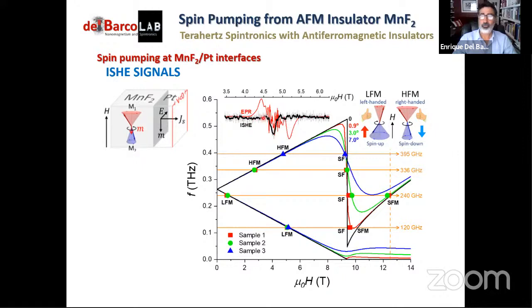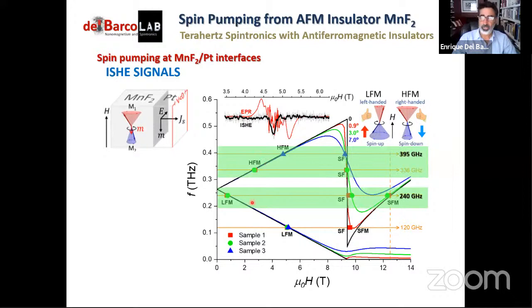But the same doesn't apply to the electric signal. In all cases, all these dots, we have the electric signal exactly where we have the center of the spectroscopy signal. And from now on, I'm going to show you results at two different frequencies. One low frequency, where we can explore the low frequency mode, the spin flop transition, and the quasi-ferromagnetic mode. There's a typo here. This should be a Q, not an S. And then a high frequency, where I will show you two different frequencies for a particular reason I will let you know later. But in this high frequency range, we look at the high frequency mode and also the spin flop transition. We cannot reach the quasi-ferromagnetic mode because we have this limiting magnetic field.